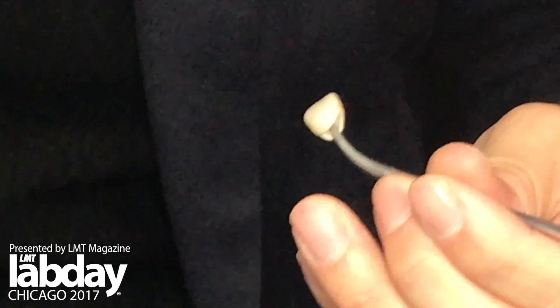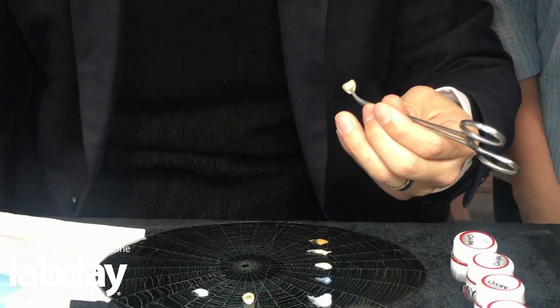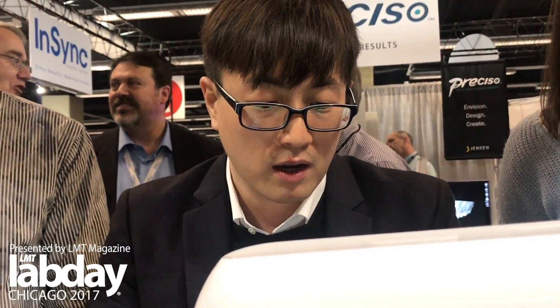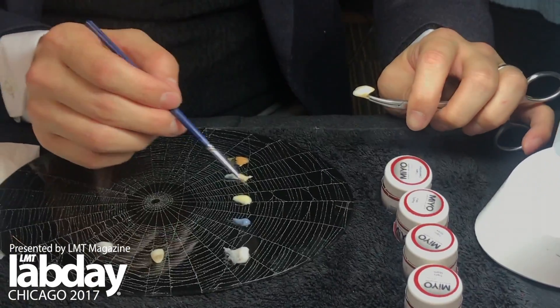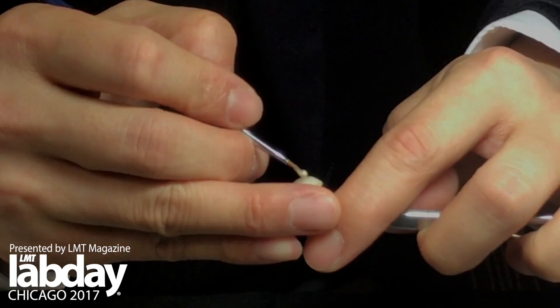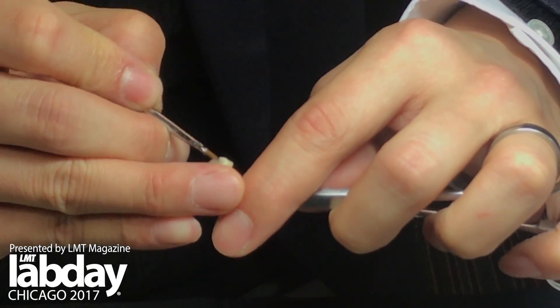What I like to emphasize is that I never make brush strokes. I see a lot of people do this on zirconia — it leaves streaks, and when you fire it you see spots because of that. Like applying opaque, you let the brush kind of float on top and move the thickness around the same way, so there are no brush strokes. Then I use a translucent stain. This might look like it has a lot of color and is very dense, but after you fire it, it's very translucent — it adds color but it's translucent. I usually apply this on the area with a little higher value zone, the body one-third.